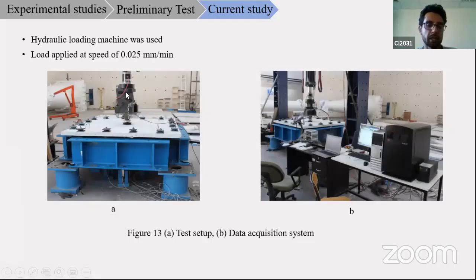Here, again, a hydraulic load machine was used to load the specimen at the midpoint, and the load was applied at a speed of 0.025 millimeter per minute through a steel plate of 150 millimeter diameter. A load cell was used to measure the load, and a displacement transducer was used to measure the vertical displacement. Here, we see the data acquisition system was used to collect the data.